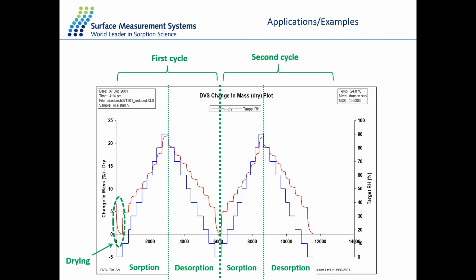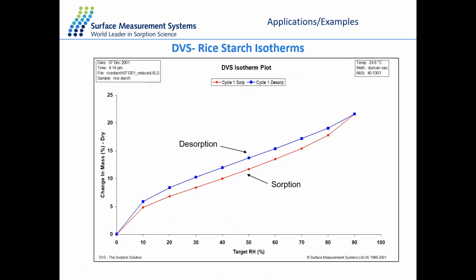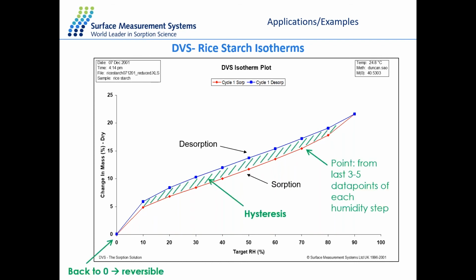high uptake of water. Now, if we take each equilibrium condition at each partial pressure stage and we plot it versus the relative humidity, we can see here that we get our isotherm plot. So what extra information do we get from this specific plot? You can see here there is a nice gap of hysteresis between the absorption and desorption, which usually indicates that the sample is having a bulk absorption, which means that the material has a very, very high affinity for water. And so water tends to penetrate through the sample and try to stay inside the sample as much as